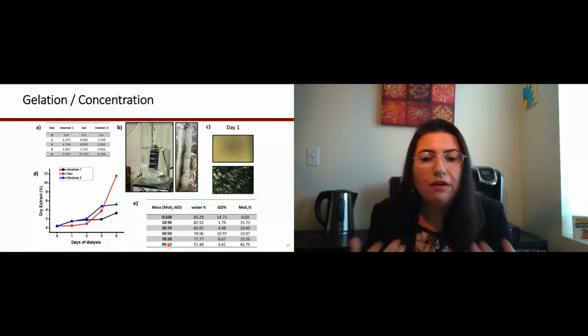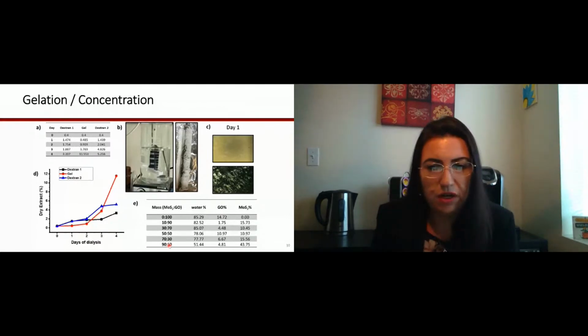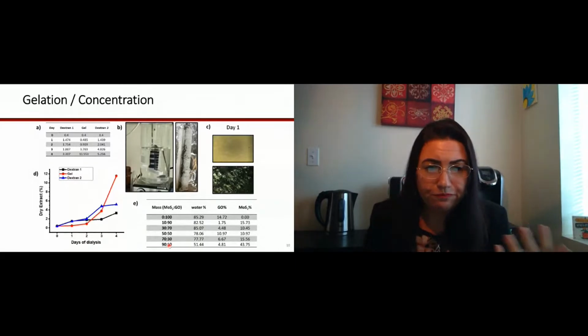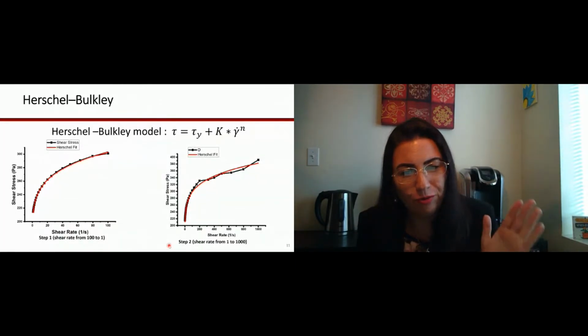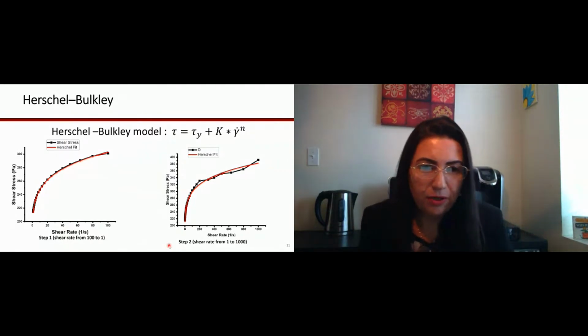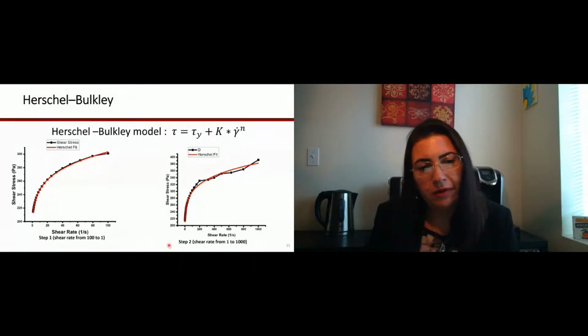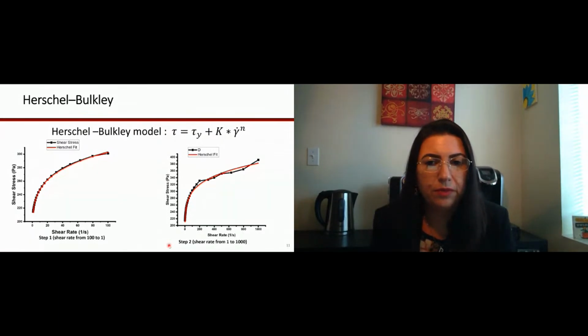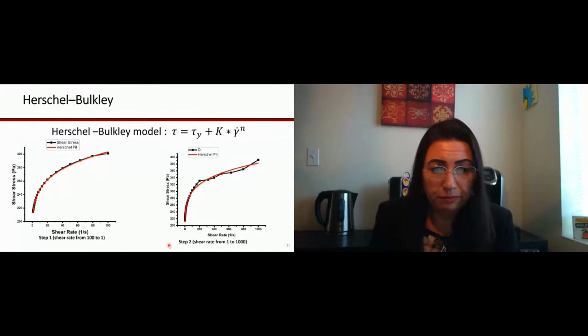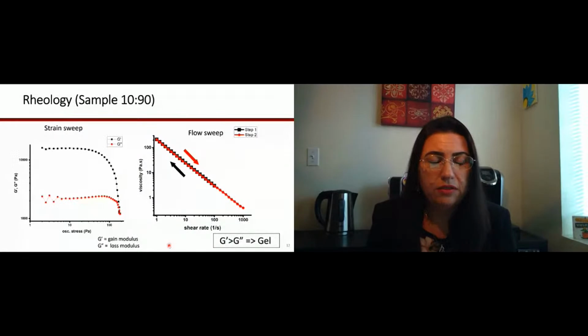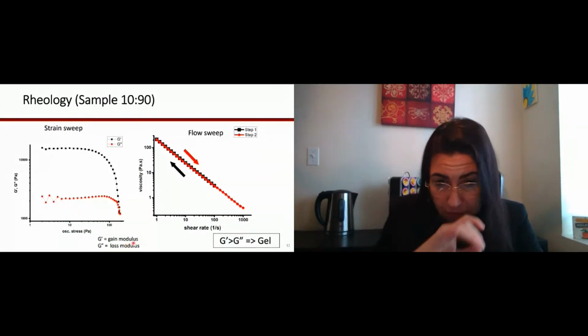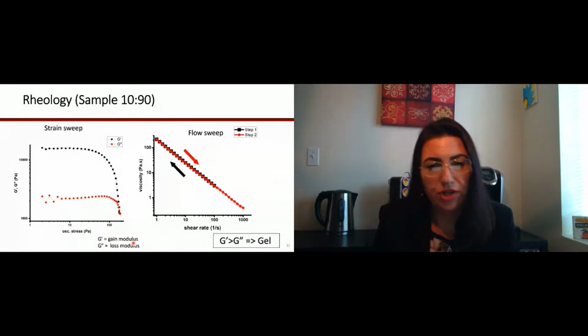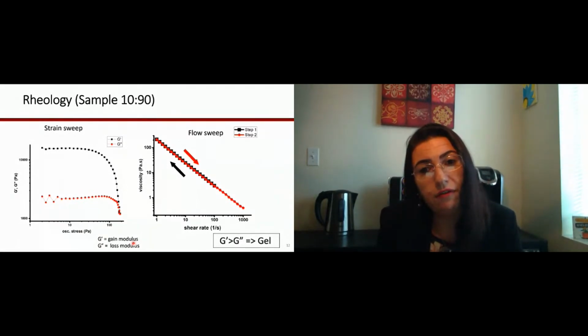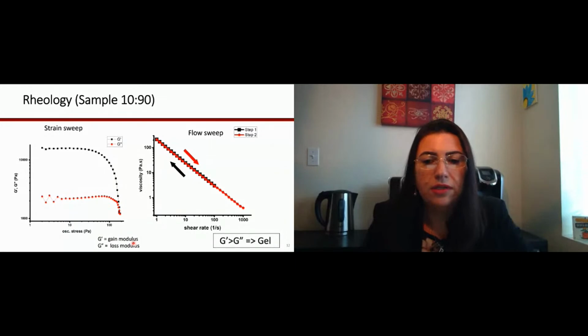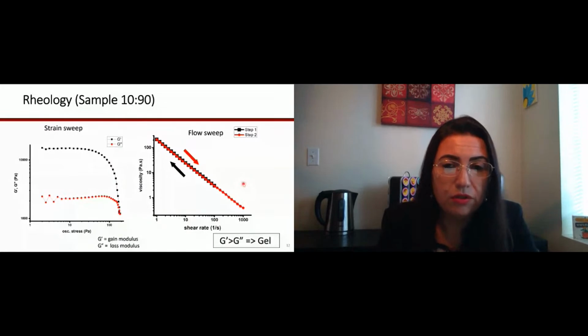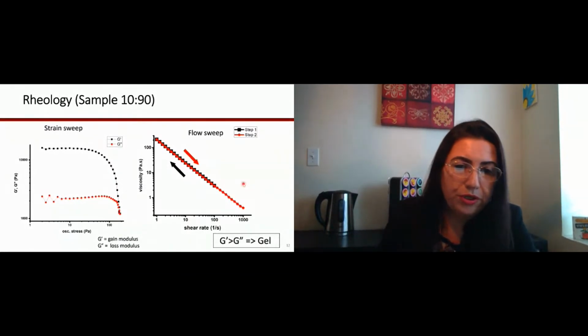So this was great. And even though the MoS2 was bulk, we still were able to mix it well and obtain the gels. Having obtained these different concentrations of gel, we have to understand a little bit of the rheology. Leanne just went over a lot about that, so I won't go into much detail because she did a great job. What I want you to get from here is really just how the material behaves and how we proved that this was actually a gel using the rheometer. So there were 2 points. In our materials, our storage modulus was always above the loss modulus, which means that for all our materials, we actually obtained a gel. And what was really interesting too is that our material was viscoelastic. In the graph of the flow sweep, the material went back to its original property almost every single time. It went almost to the same point it was before.